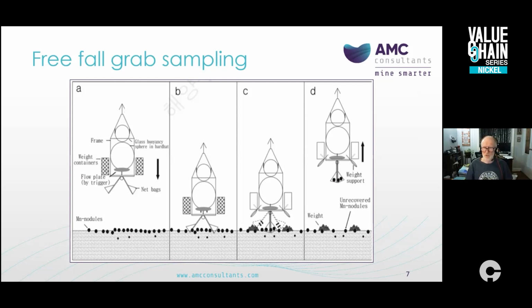The big advantage of freefall grab samplers is that they can be deployed and retrieved independently without the need for winching, so several samplers can be efficiently deployed without delays. The disadvantage with them is that smaller nodules may be lost through the netting, and the biggest nodules may be too big to be caught in the net bags, and the recovery may only be partial.